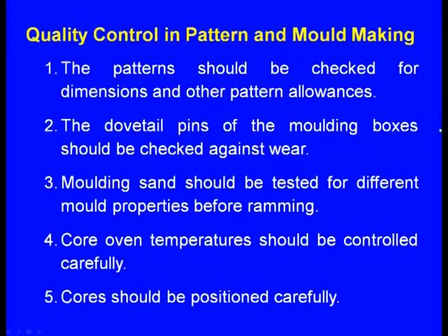Sometimes it is possible that when we use these pins for several components, then what will happen? These pins will undergo wear. If there is a wear of 1 mm, then what will happen? The moulding boxes can displace by 1 mm. In that case, there will be a misalignment between the drag and the cope. That is why we always have to check whether the dovetail pins are in good condition or they are worn out. If they have already worn out, we must replace them. So, that is the quality control in the maintenance of the moulding boxes and the dovetail pins.